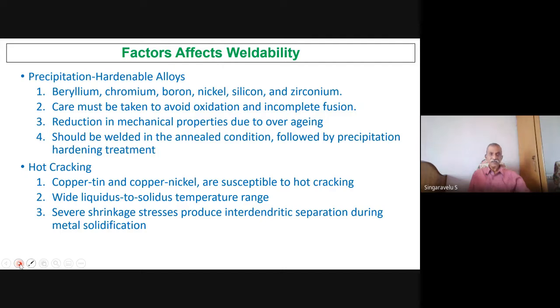Okay? Precipitation hardened alloys: beryllium, chromium, boron, nickel, silicon, all those elements have been added. That should be taken care of during oxidation. Okay? Reduction in mechanical properties can occur due to over-aging. What is called precipitation hardening and aging alloy? There are certain elements like these added in this. These come out as precipitates which enhance the strength. And if you do over-aging, that is, the alloy is kept at higher temperatures during the welding process for some more time during the cooling process, this may reduce the mechanical properties. It should be welded in the annealed condition, followed by the precipitation treatment.